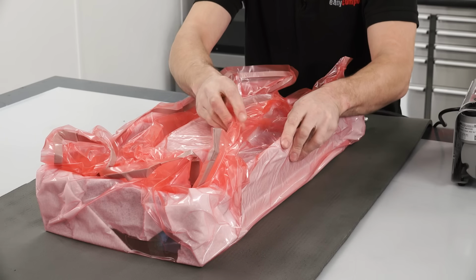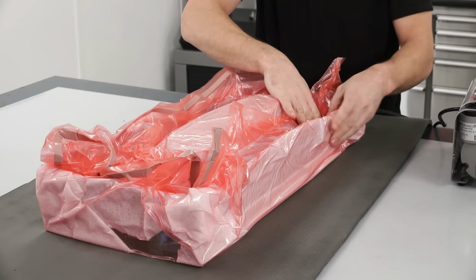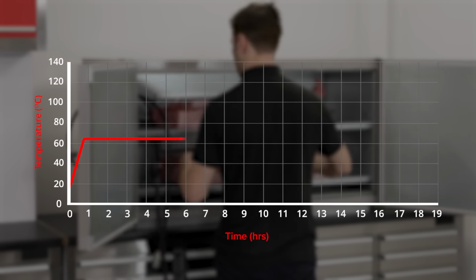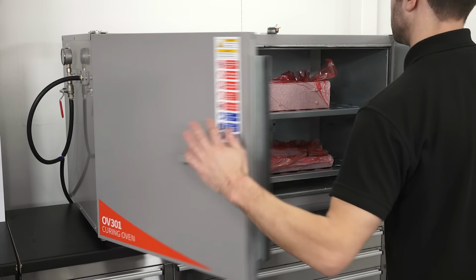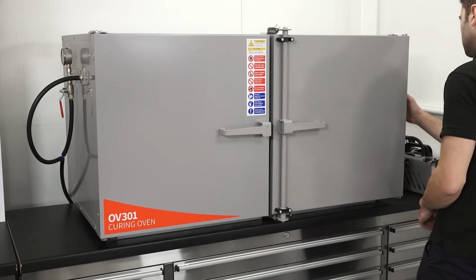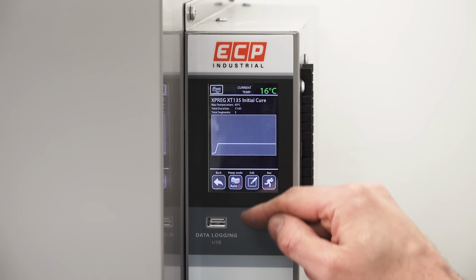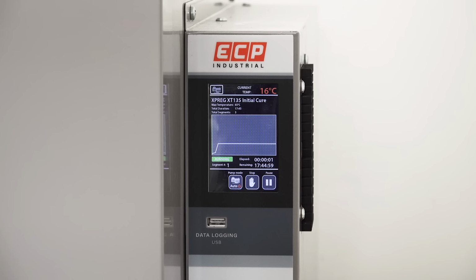A drop test is performed before the moulds are loaded into the oven for the initial cure. This is done at a low temperature of 65 degrees C for several hours. If you're not familiar with tooling pre-pregs, this is really where they differ from regular ones. With the low initial cure temperature, it allows them to cure without causing excessive expansion on the pattern.